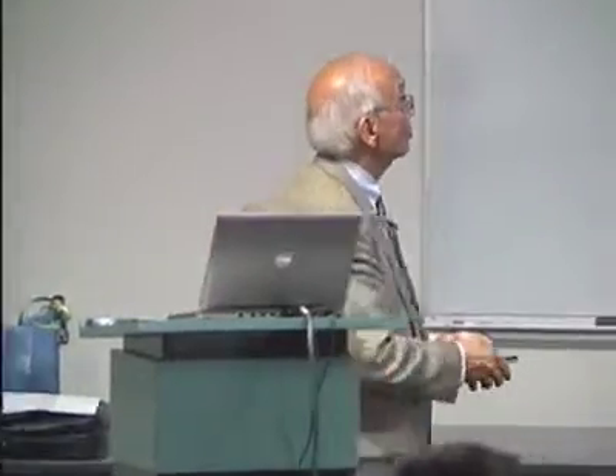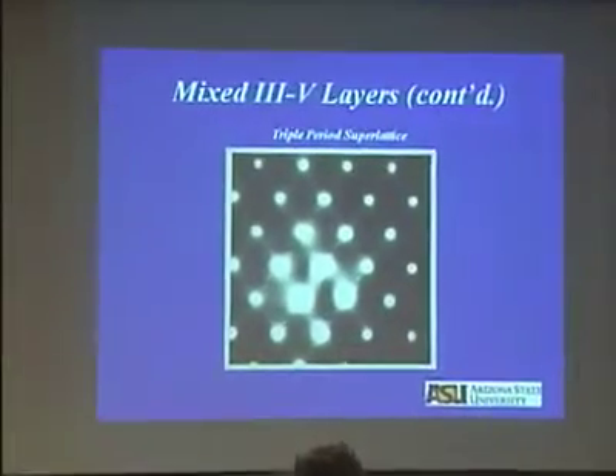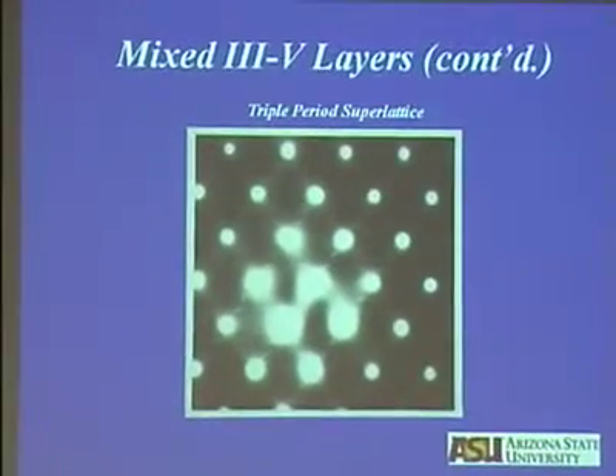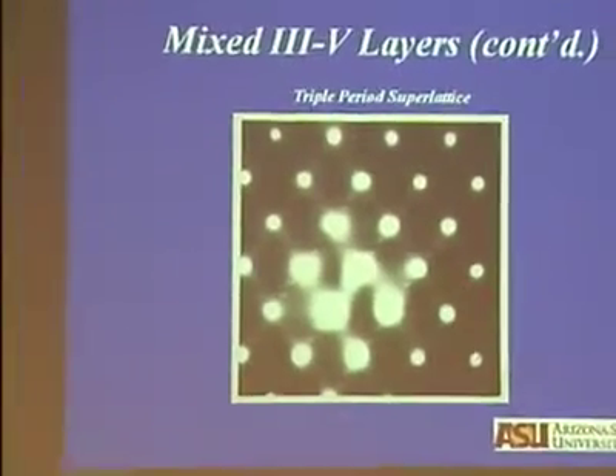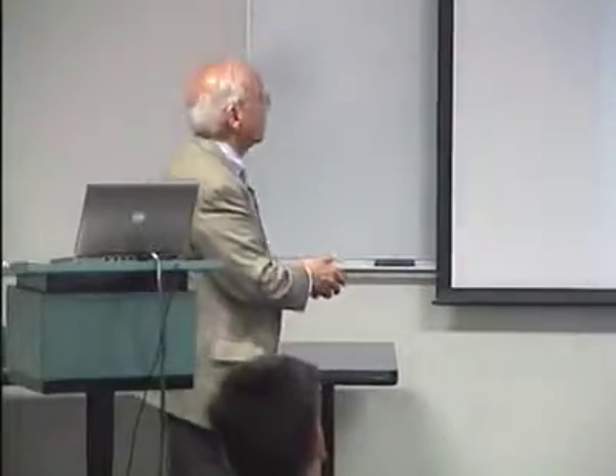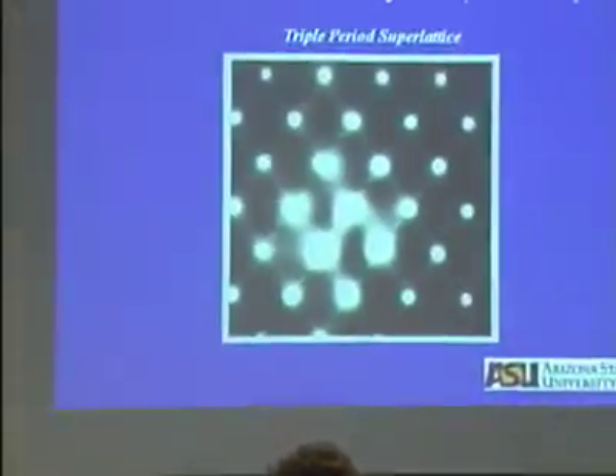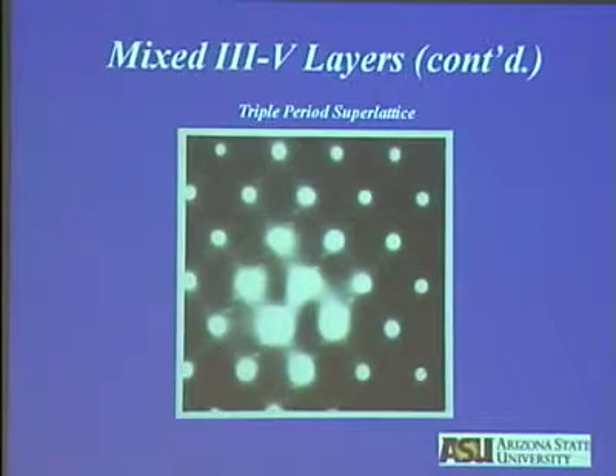Now, you can also produce triple period superlattices in these materials by changing the reconstruction. Earlier I was talking about 2x4, but you change the reconstruction to 4x2. Reconstruction, we don't learn much about it in material science, but in applied physics it plays a major role. But it's a simple concept: the atoms on the surface behave differently from atoms in the bulk. You can produce these reconstructions by changing the 3-5 ratios in your growth system.